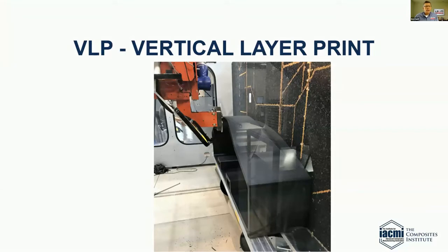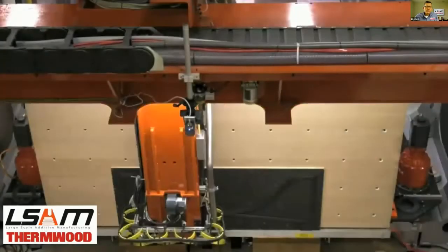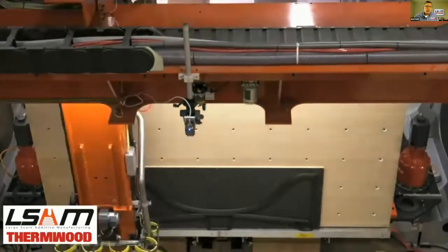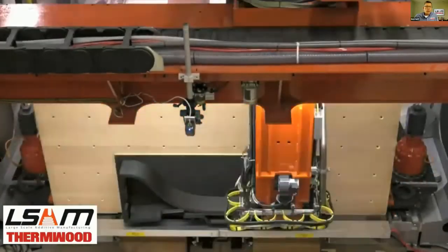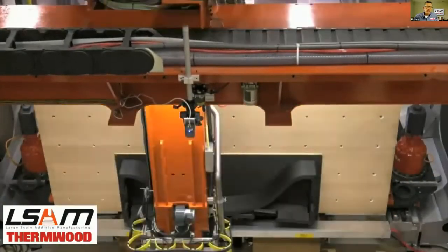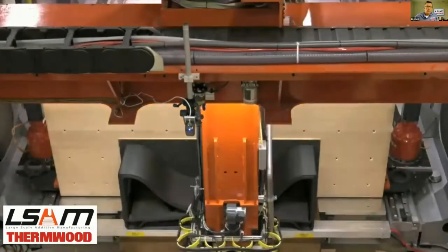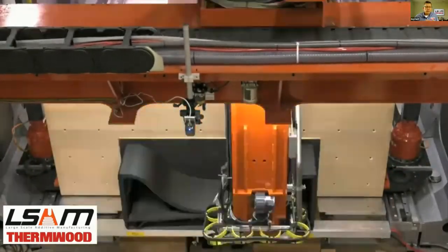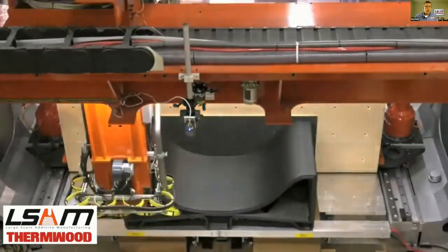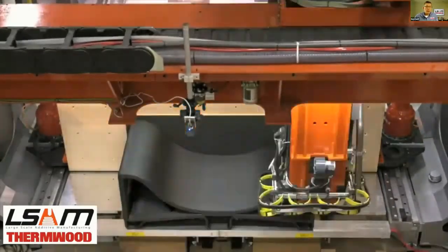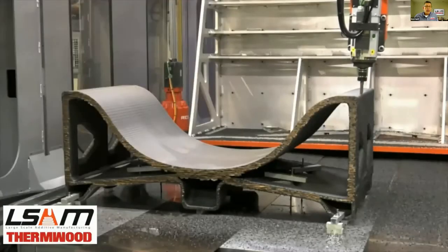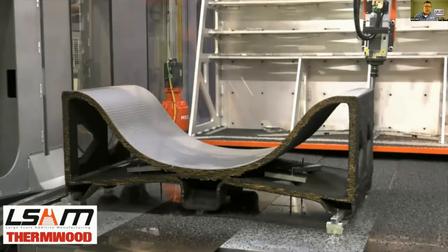Another thing that's really interesting is something called vertical layer print, or VLP. And with the continuous cooling process, you don't actually have to print horizontally, you can print vertically. And that's a really good option for making tools. This is a tool here that's being printed on a vertical wall on a beadboard. And you can see that in this time lapse, the wall keeps moving backward from the print head. The very area where it's being printed isn't supported at all. It's only supported once the wall moves back over the table. And you can get some really nice shapes out of this.